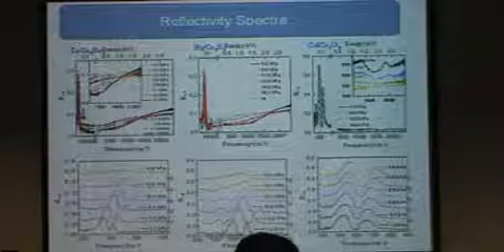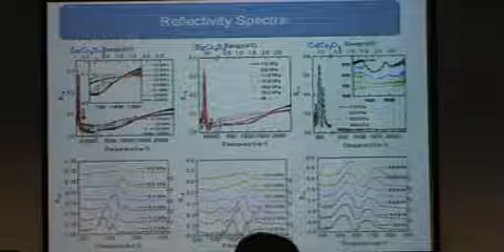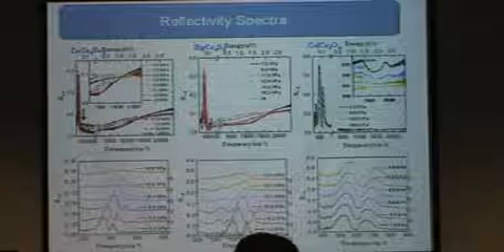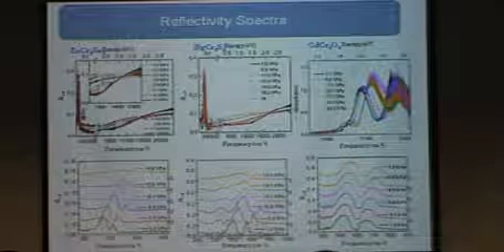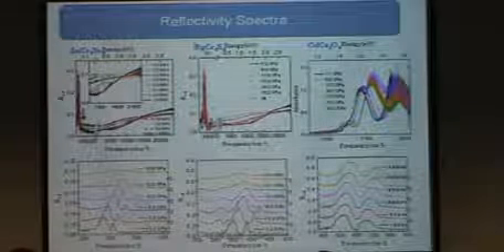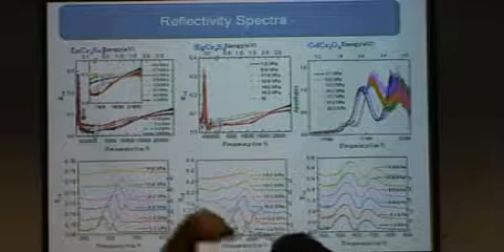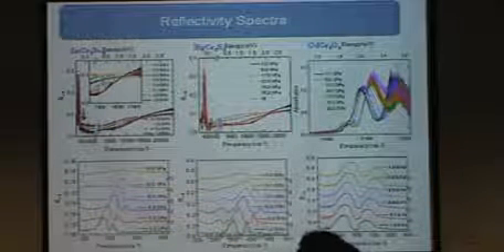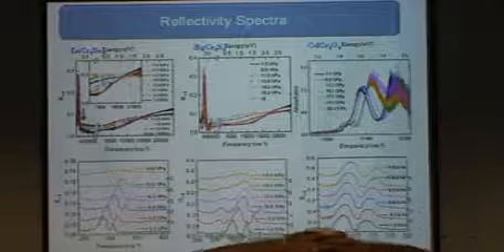But if you zoom in on this frequency range, you see some electronic transition. To get access to these transitions, we did an absorption measurement, so that's the absorption spectra. Later, for interpretation, this absorption spectra was used for cadmium chromium oxide, but for sulfide and selenide, the reflectivity spectrum.